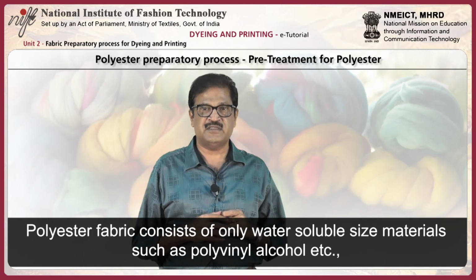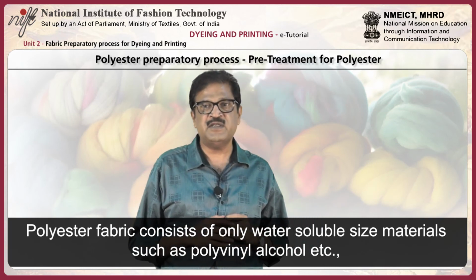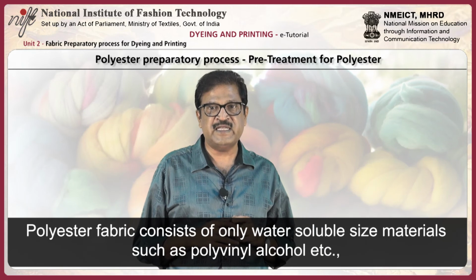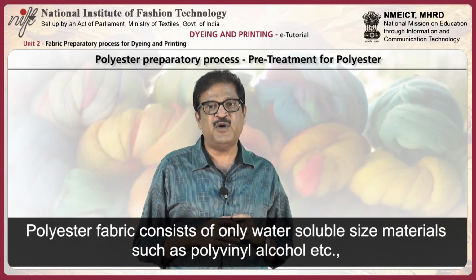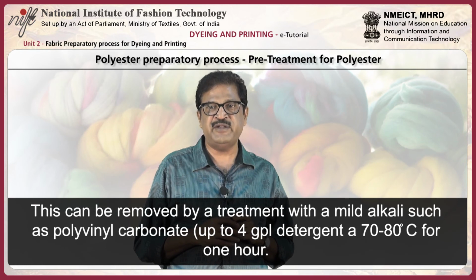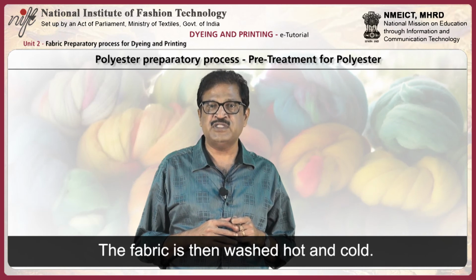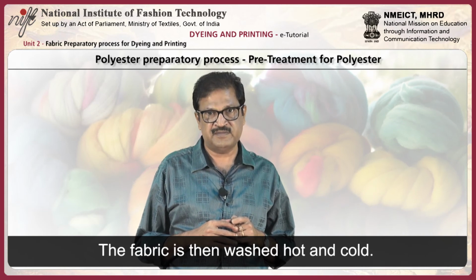Desizing of polyester. Polyester fabric consists of only water soluble size materials such as polyvinyl alcohol, which can be removed by a treatment with a mild alkali such as sodium carbonate up to 4 grams per liter detergent at 70 to 80 degrees centigrade for 1 hour. The fabric is then washed in hot and cold water.